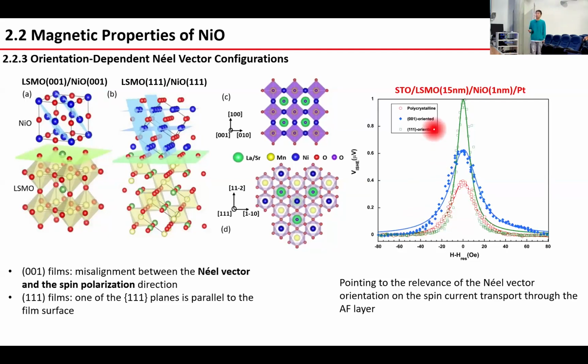So we prepared 1 nanometer nickelate with these different crystallographic orientations, where the 111 oriented shows the maximum inverse spin Hall effect voltage, and then the 001 oriented, and the polycrystalline reaches the minimum inverse spin Hall effect voltage, which directly points to the relevance of the Néel vector orientation to the spin current transport through the antiferromagnetic layer.